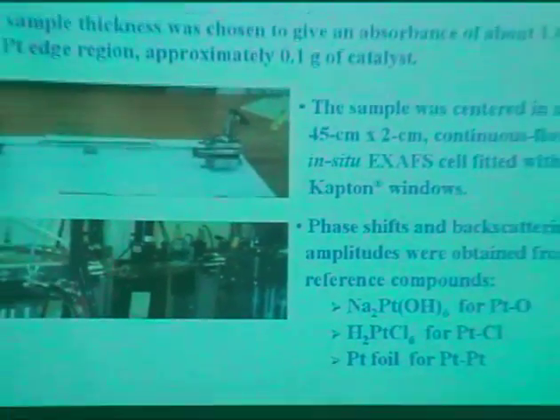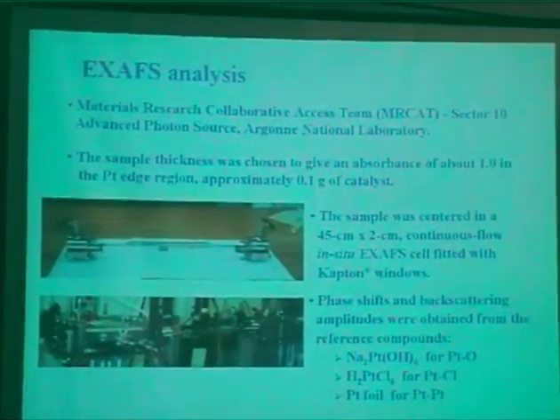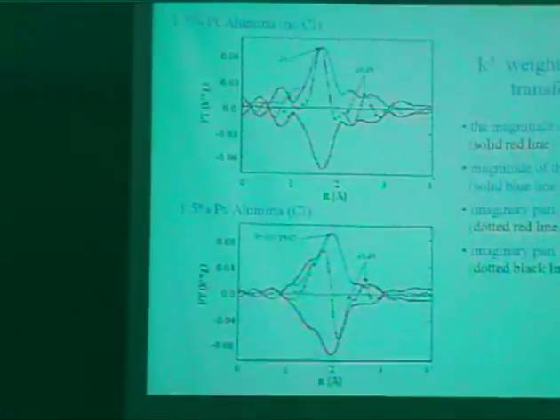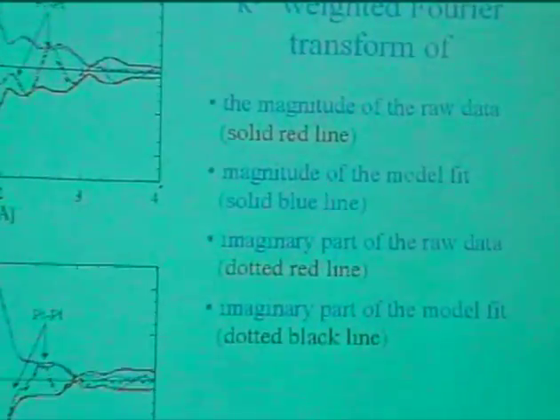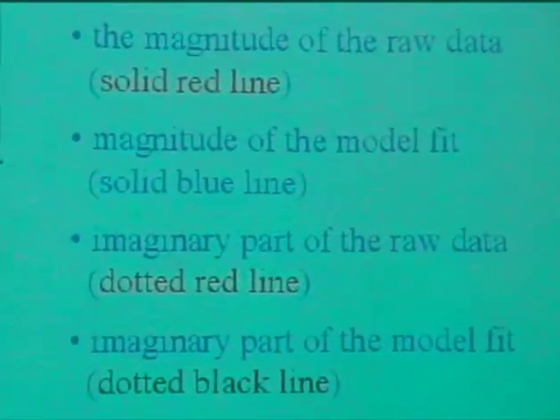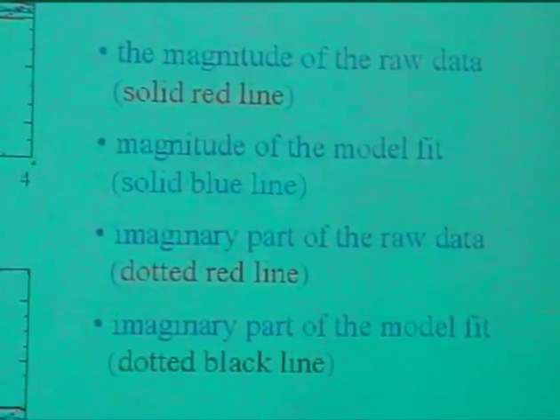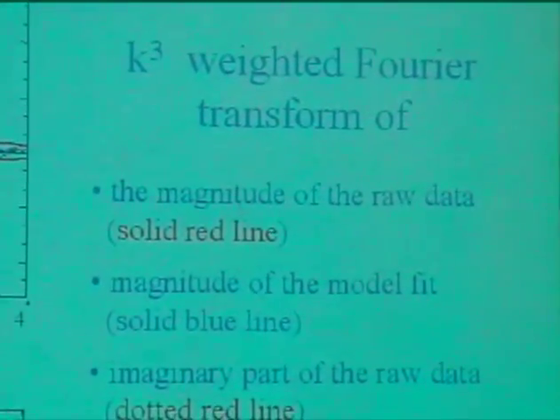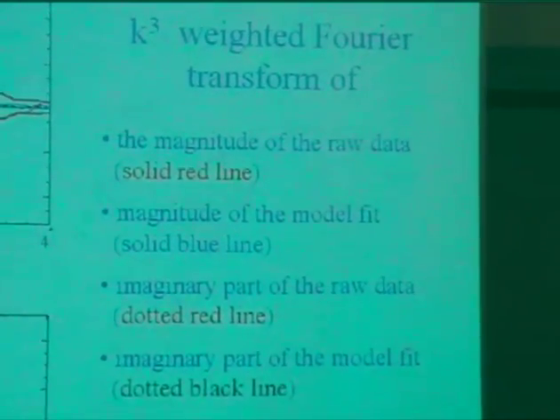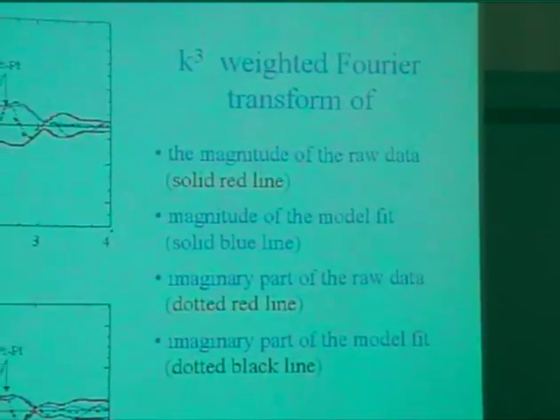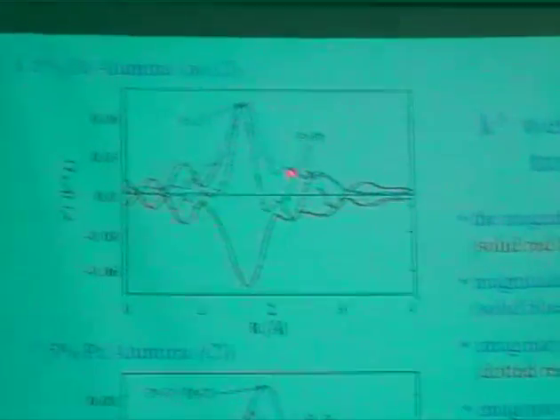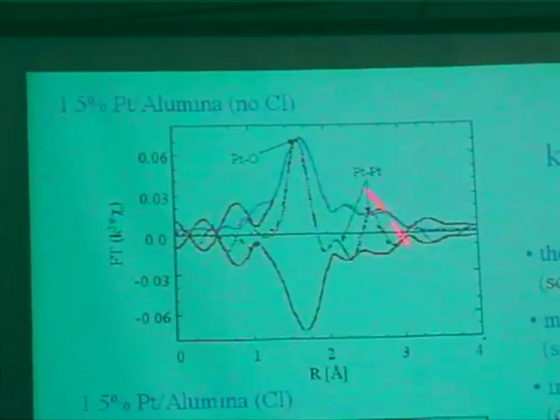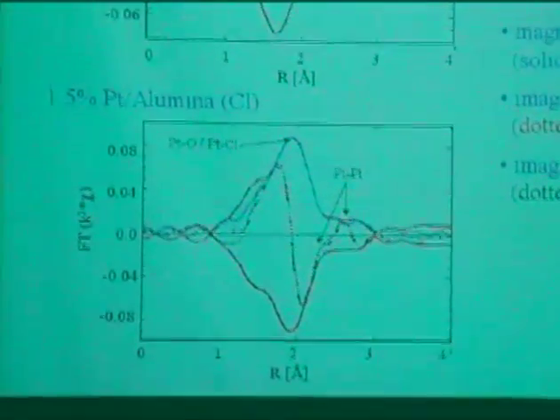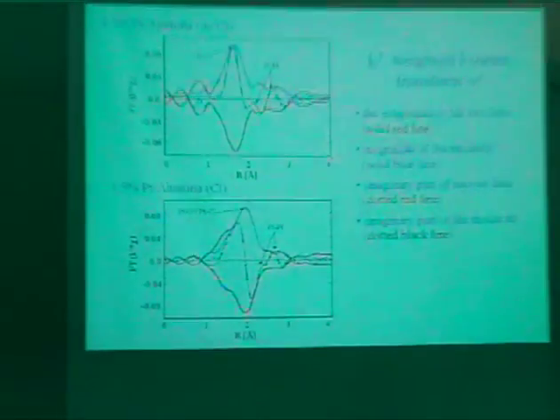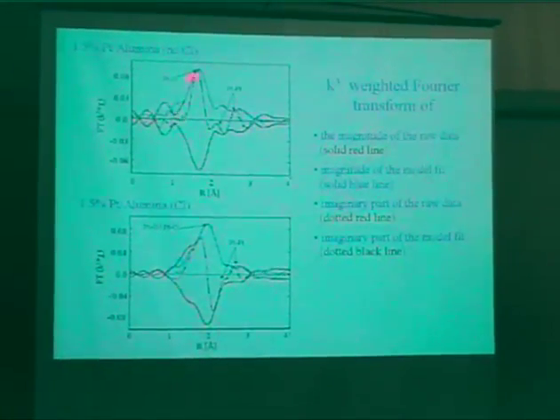And so he can look at the spectra and pretty much decide what's important, what's not important, and that's why it's important to know what's happening with the activity. Because if you don't have the activity data, it's not that simple. Because you have to fit this in order to interpret the data. Okay? So here we have both the magnitude of the raw data for the no chlorine and the chlorine catalyst, and just by inspection you can see that these are indeed different. And then we have the model fit in the blue line.